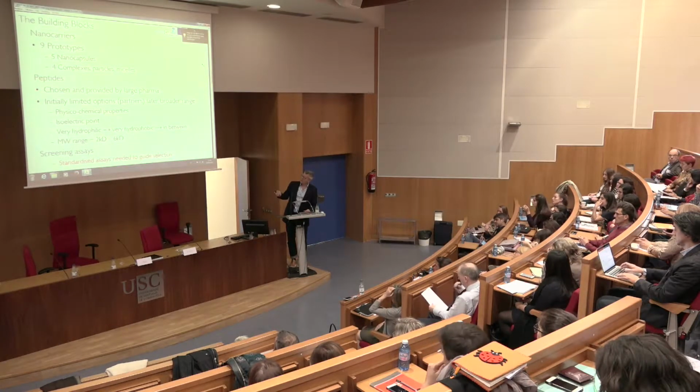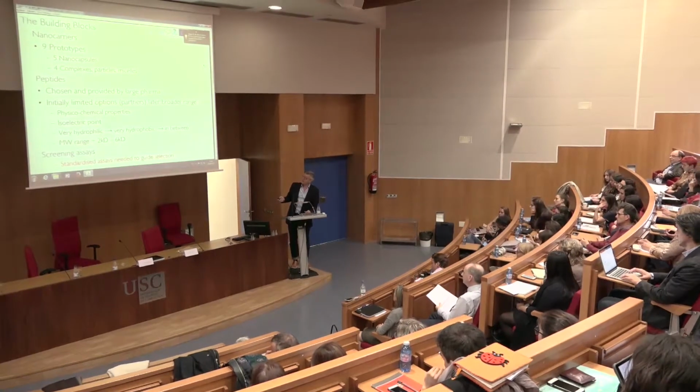One where we turned out to then have a broader range was around the isoelectric point, the size, the molecular weight of the peptide. And then here, quite important in terms of matching up with the prototypes was this, well, are they hydrophilic, are they hydrophobic? Because, of course, nanocarriers very often will use some hydrophobic interactions to form the nanocarriers. And one of the challenges that we dealt with was that a lot of the peptides were very hydrophilic. And so some of the learning that had to go into this was actually the adaptation of this matching of physical-chemical properties of peptides with what the different types of nanocarriers could do, and then throughout the course of the project to bring in new prototypes that could accommodate these peptides.